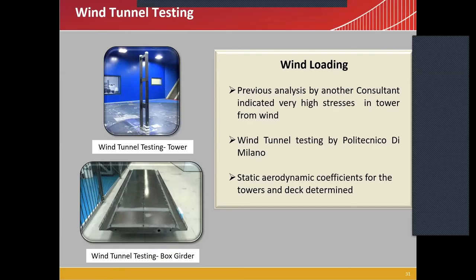Since this bridge was designed in the early 1970s and built in 1973, of course the code requirements were different than nowadays. So in order to verify the aerodynamic stability of the bridge and the towers, wind tunnel testing was performed. Wind tunnel testing was done by Politecnico di Milano. And also the other consultant, prior to when we started this project, did the analysis, and their analysis resulted in very high stresses in towers from the wind. After the wind tunnel testing, static aerodynamic coefficients for the towers and deck were determined.